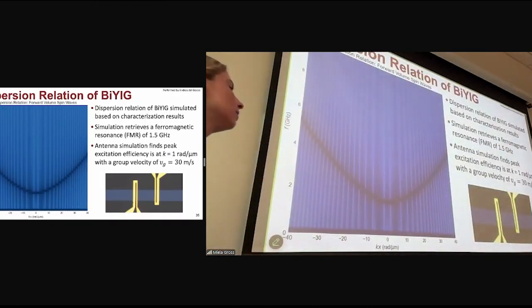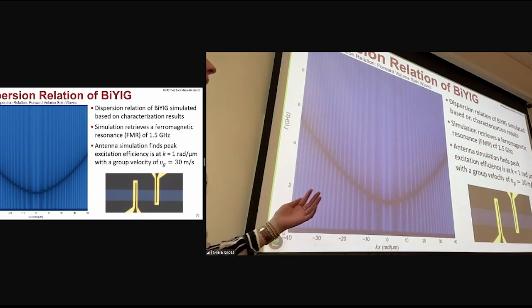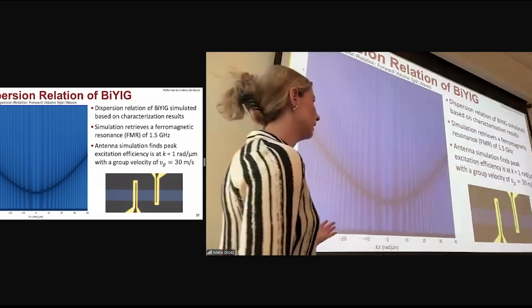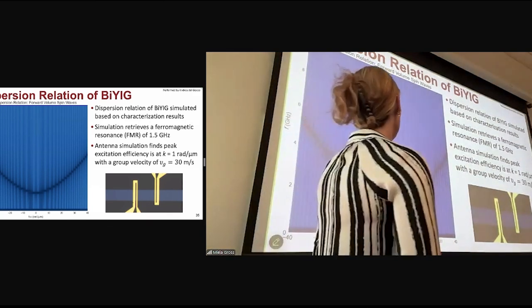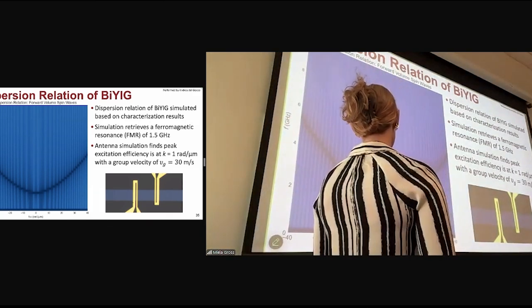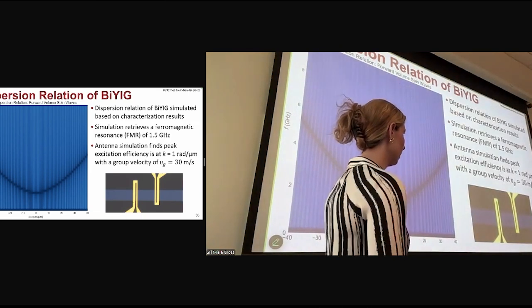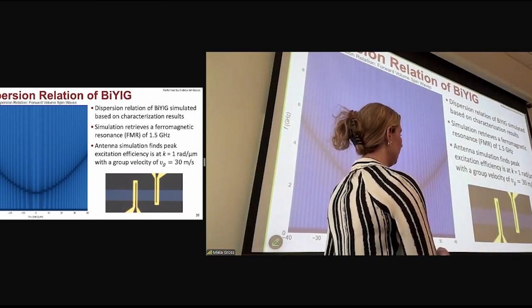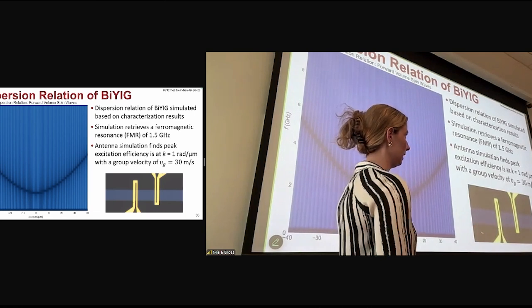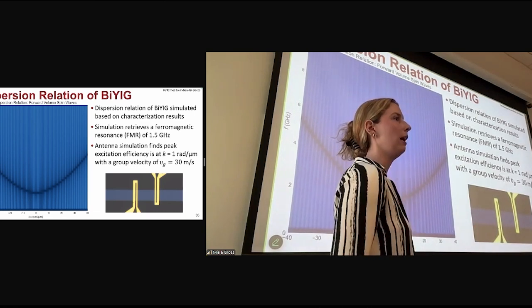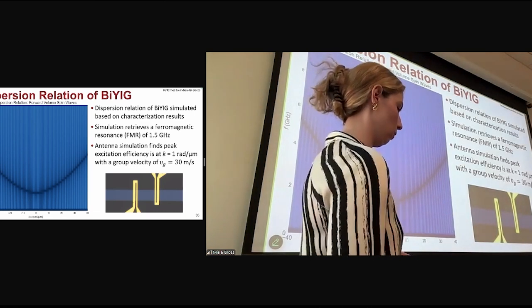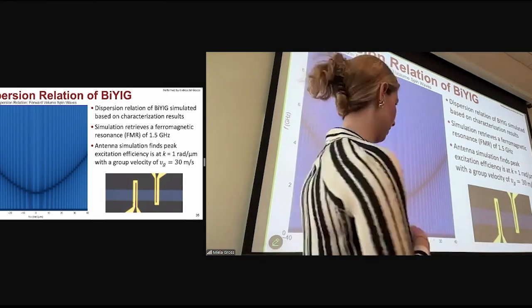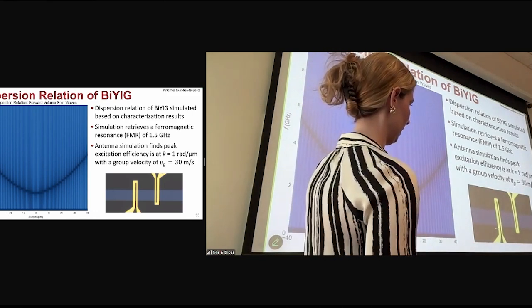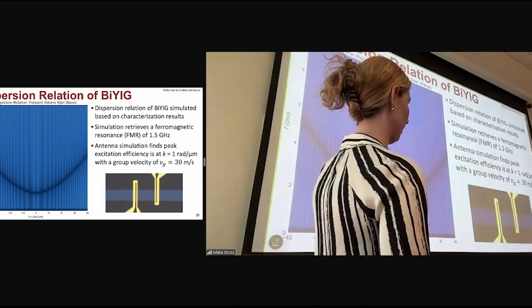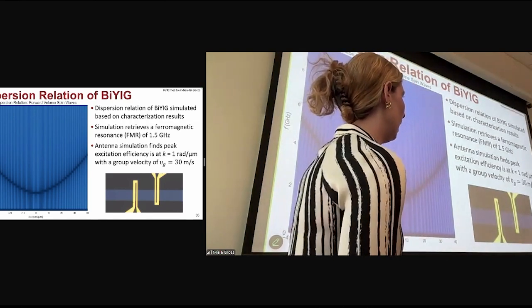So we used the characterizations in the past slide, and my colleague Andrea was able to simulate the dispersion relation of the bismuth-YIG racetracks and find a zero field FMR frequency of around 1.5 gigahertz. And he also was able to take the dimensions of our antennas that we patterned here on the right and see what kind of magnons we can excite based on superimposing this excitation efficiency onto the dispersion relation.